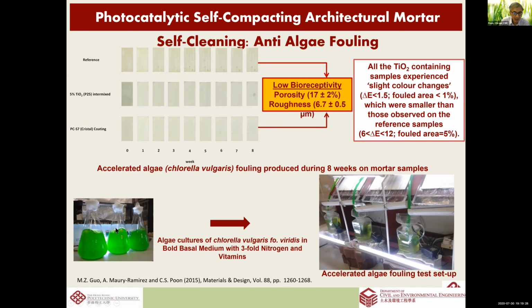What we try to do is to grow the algae and then run it through this. This is a setup that we made in the lab, to run this algae in solution through this layer of construction materials, some of it coated without TiO2, with TiO2, and with different coating methods. Then we see how much algae is growing on top of the layers, with the UV on. This shows the reference, the reference without TiO2, there's a lot. I'm sorry, it would not be very clear, but you can see there's a lot of algae growing on the surface.